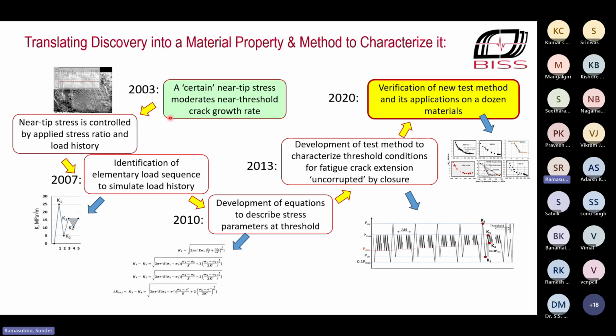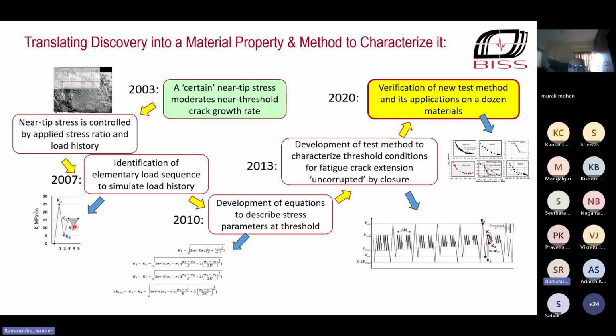So it turned out that there's a certain near-tip stress which probably moderates near-threshold crack growth rate. That stress should be controlled by applied stress ratio and load history. So I derived the equations for what happens when you have a load history. That is an overload, an underload, followed by the baseline cycling. So I'm determining threshold under the baseline cycling, but I can periodically apply these overloads and underloads to punch in a desired near-tip residual stress. So that's how an elementary load sequence was designed to simulate load history.